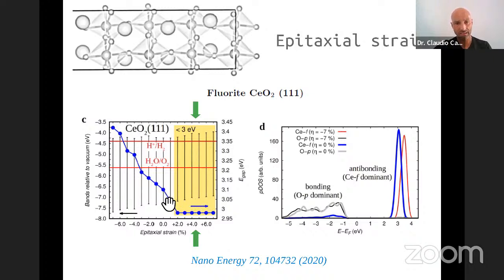So we found out that, in fact, at zero strain, so if you don't apply any epitaxial strain to the material, you have a material with too large an energy band gap, 3.2 electron volts, to use it for direct photocatalytic applications, right? And also the straddling of the two energy levels of interest for water splitting was not too good, right? So this point here was too far below the OER energy level, right?